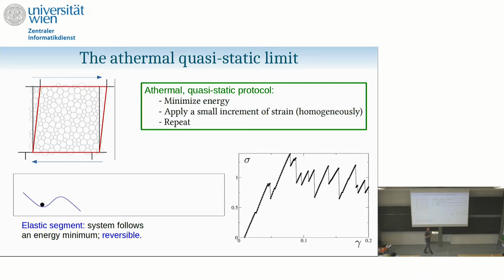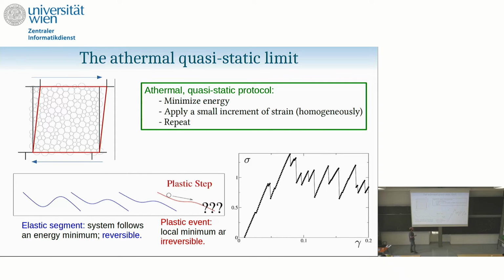And what it corresponds to in the potential energy landscape is that the basin of attraction where your system lies will shrink. And at some point, you have to reach a catastrophe, meaning that the minimum suddenly vanishes. So you shrink your basin of attraction to zero, and now this point, the minimum, becomes unstable, it becomes a saddle point, and now the system has to go somewhere. So if you look at a stress-strain curve, what I show here is a small system. It's 20 particles on the side, so about 20 by 20, 400 particles, something like that.